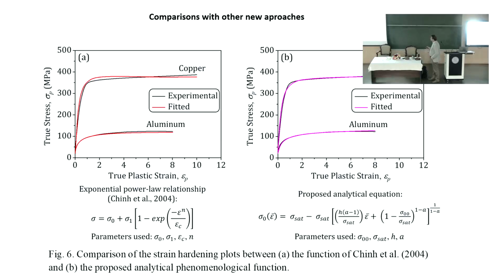Here you are selecting one which was a Chinh empirical function. I presented it at the very beginning, in 2004. And they were presenting curves for aluminum and copper. You see the fitting, what they could achieve. And it's just empirical, no crystal plasticity. So we did the same case, we took the same. We used our function here. Here they have 4 parameters. You also have 4 parameters, but the function is different. And then we did the fitting, and there is an improvement.